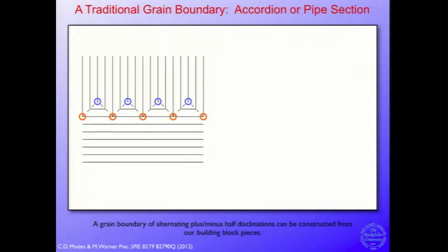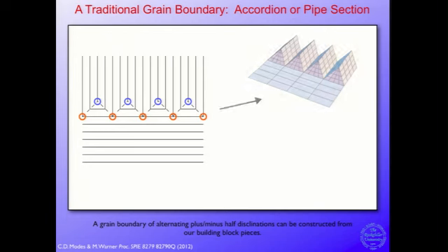Okay, another thing that comes up all the time in nematic textures is grain boundaries. So you can imagine writing down just a plus or minus 1/2 grain boundary that connects a director going this way to a director going that way across some length scale. So this one, if you strain it a little bit, the Gaussian curvature on the positive side kind of makes this little series of ridges.